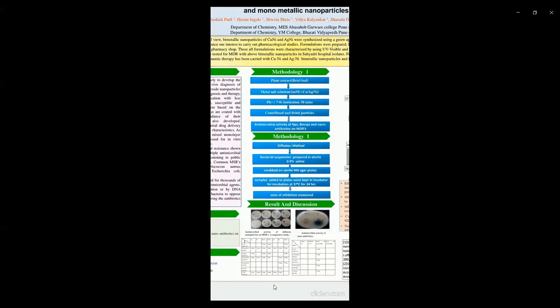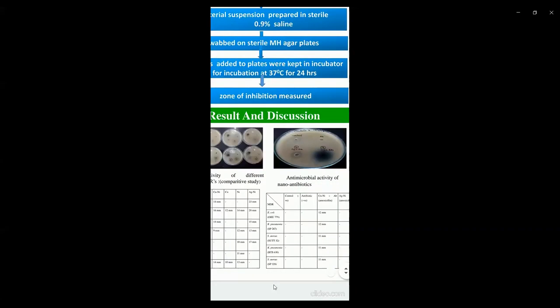First, using the green method, monometallic nanoparticles like copper, silver, nickel, and bimetallic nanoparticles like copper-nickel and AgNi were synthesized using betel leaf extract. On 6 to 7 MDR pathogens such as E. coli, S. pneumoniae, K. pneumoniae, etc., antimicrobial activity was carried out using the same mono and bimetallic nanoparticles, which resulted in better efficiency for bimetallic nanoparticles.